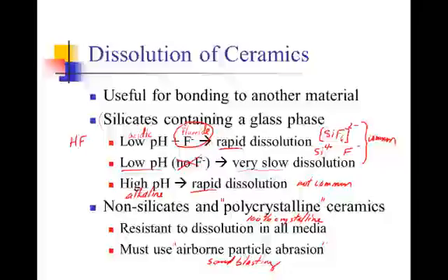And there are polycrystalline ceramics such as zirconia, which is zirconium oxide, for which it was recommended for a long time not to use sandblasting on them. That was thought that it would weaken the material, and now manufacturers have realized that sandblasting can be used on zirconia as long as it is done very lightly and carefully, and then it can actually form a stronger material and a rough surface that's easy to bond to.